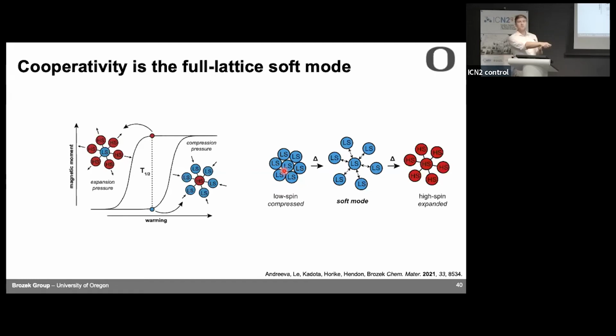When you move to a high spin magnetic system, the bonds are much weaker. The reason these dynamic metal triazolate bonds act as a soft mode is because it's a vibration that's taking those strong low spin bonds and stretching them out. Eventually that vibration stretches them out so much that all of a sudden the MOF switches into the high spin state. So that's how we think it's acting as a soft mode.